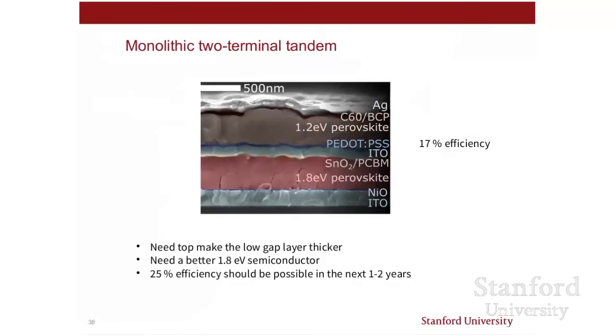And here you see the cross-sectional SEM of a two-terminal tandem. Right now, we're at about 17% efficiency. And we understand what some of the problems are. Our 1.2 eV material is far too thin. We just haven't figured out how to deposit a thick, high-quality film yet, but I think that will certainly be figured out. And we needed a 1.8 eV band gap to have proper current matching, but we also need a better composition for that band gap, and I see no fundamental reason why that can't be done. So I expect this efficiency to rise very quickly.